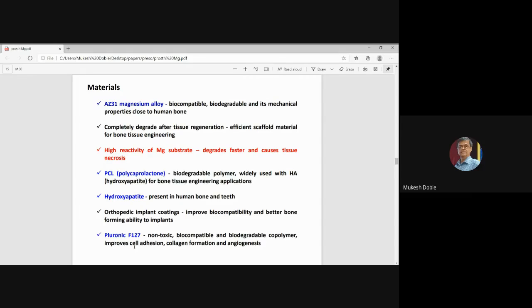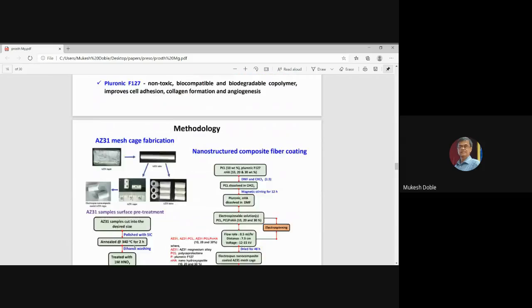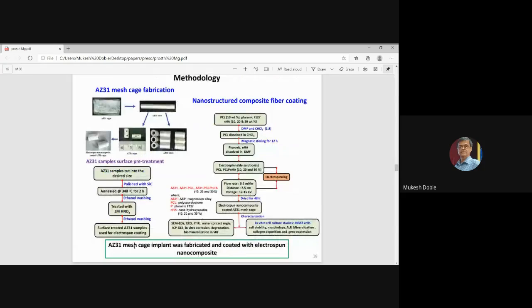We also used a polymer called Pluronic F127. It's a non-toxic, biocompatible, biodegradable copolymer. It's approved by FDA. It improves cell adhesion, collagen formation, and angiogenesis also. So we used that in combination. And this is almost like a surface active agent. So we worked on designing magnesium cages for long bone segmental defect application, just like the titanium mesh cage. So we took magnesium rods, and then we made that into tubes, as you can see in this picture, and then we created this sort of a cage design.